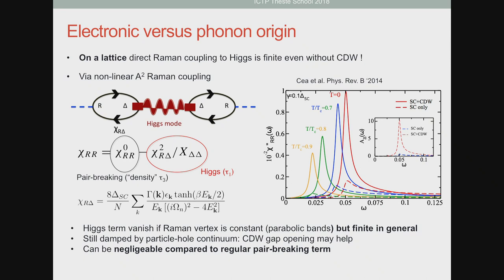In the case of niobium diselenide, it's a little bit smaller, but not that small. What you can see in the dotted lines here is this contribution. And this can be enhanced if you gap out part of the Fermi surface, this can become more long-lived, and this can gain a lot in strength. So the direct coupling mechanism is not a stupid idea and could actually work. Now, of course, in the case of niobium diselenide, such a direct coupling mechanism would not explain the spectral weight transfer between the charge density wave phonon and the superconducting peak, at least not as easily as in the Varma model. But still, it's not completely out of the question that we can see this Higgs mode in just a regular superconductor. Yes.